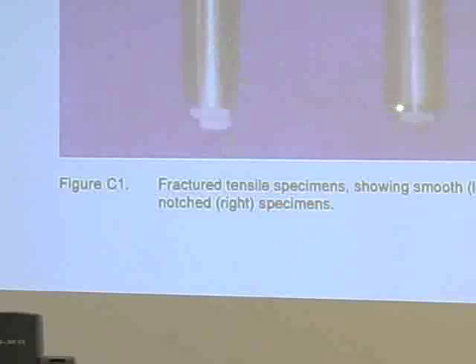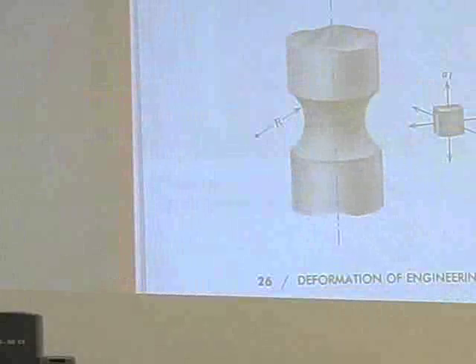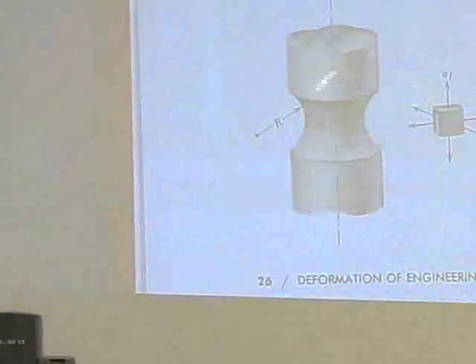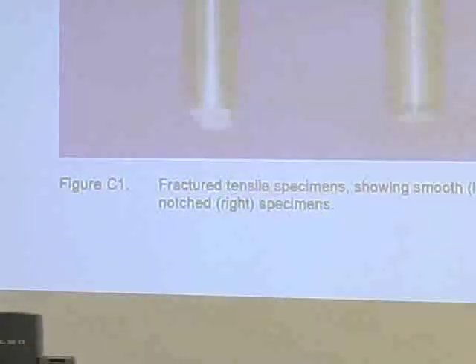We then made a notched tensile bar, okay? And basically there's a little machined bevel here. So it's larger in diameter, but the cross-sectional area at the root of the notch was exactly the same as the 1/2 inch tensile bar. So this might have been 5/8 of an inch, this was 1/2 an inch, but the fracture surface was the same. But basically what we were doing by having a notched tensile bar was introducing the triaxiality that you get from a neck. Okay, we had unyielding material on either side, whereas in a smooth tensile bar, everything's yielding.